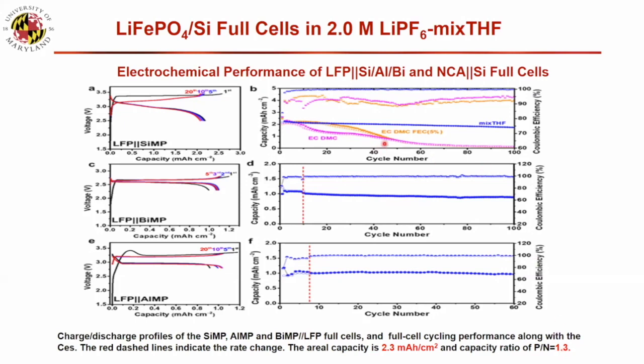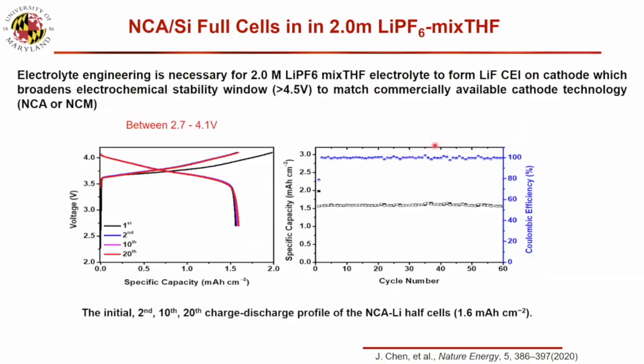Traditional electrolyte for silicon full cell quickly decays. And we also demonstrate NCA, but NCA we cannot charge to above 4.1 because that is the limitation of the THF. So right now, we developed a generation 2 electrolyte. So now we can cycle NMC811 with silicon.